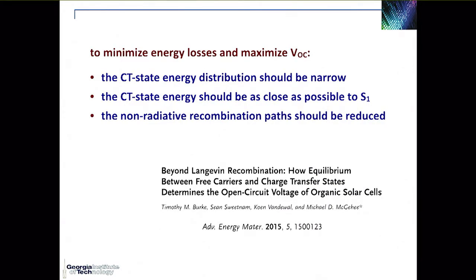A couple of years ago, Mike McGehee and his coworkers at Stanford had published a very important paper in which they emphasized that in order to minimize the energy losses that you have because of having to go from the S1 state to a CT state and then to charge-separated states, and in order to maximize the open-circuit voltage, which is very often an issue with organic solar cells, what you need to have is as narrow as possible an energetic distribution of the CT states.